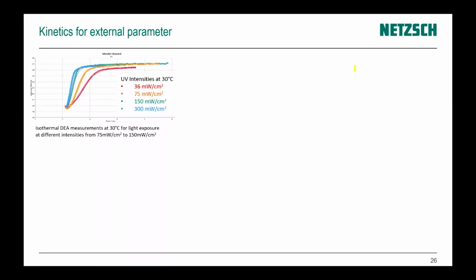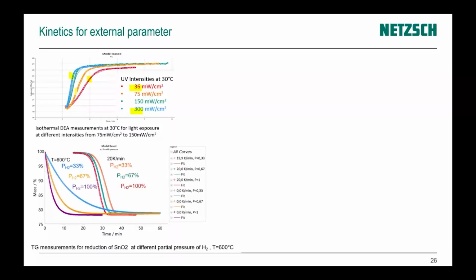We can work with external parameters like UV intensity. Here for low intensity, it is slow. For high intensity, it is fast. It is one kinetic model. It could also be measurements at different partial pressure of active gas, oxygen or hydrogen. Here is the metal reduction at different partial pressures of hydrogen.